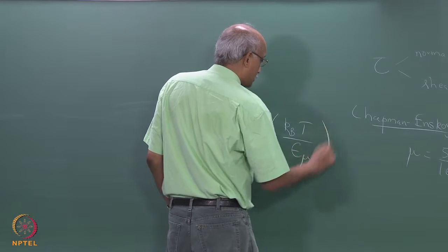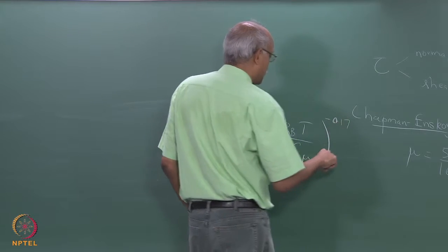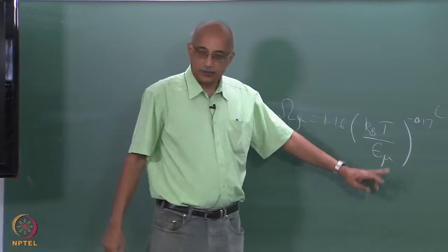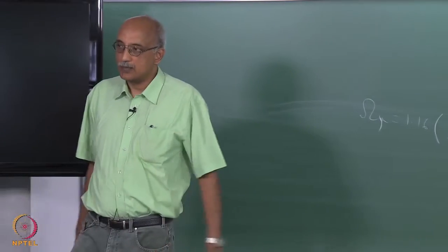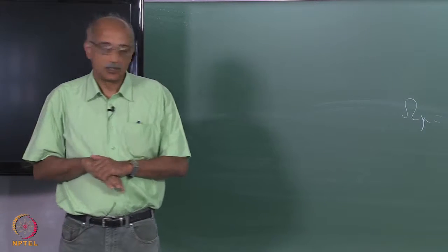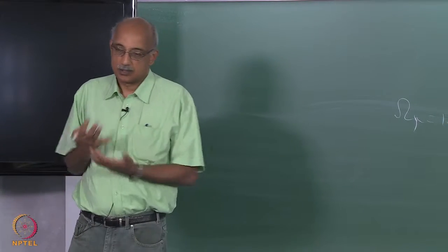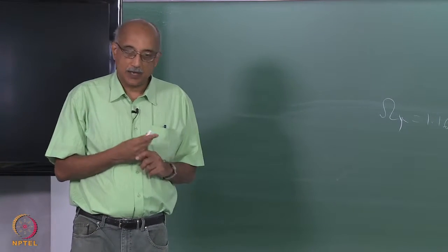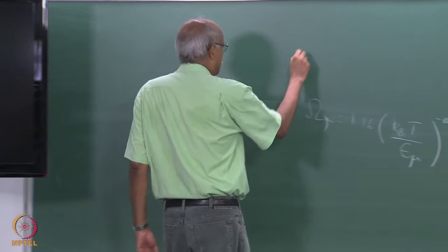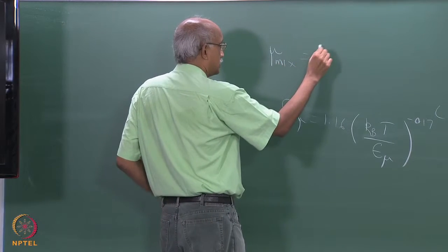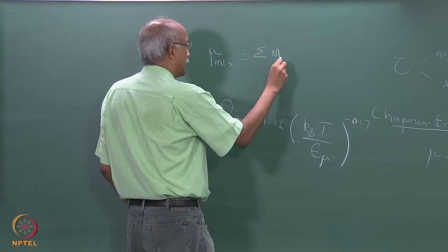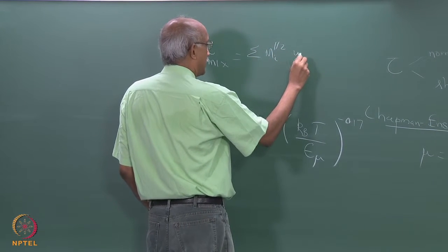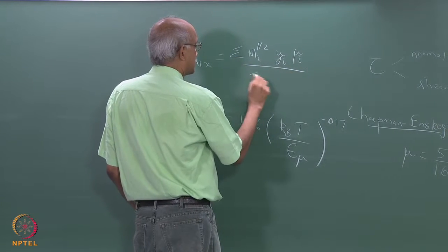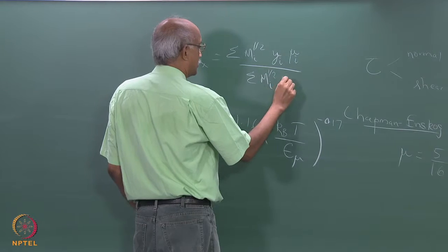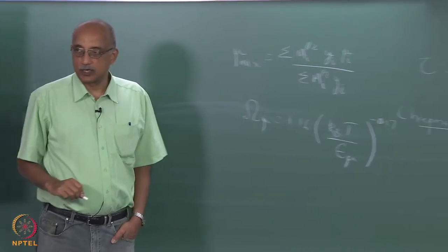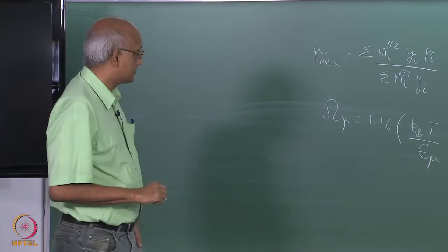So, the omega mu can be written as some 1.16 times KBT by epsilon mu to the power minus 0.17, I think, where this epsilon mu is basically an activation energy barrier for fluidity of the fluid. So, this is a general expression governing the dynamic viscosity of a fluid. If you have a mixture of fluids, you can estimate the mixture viscosity as summation of mi to the power half yi mu i divided by summation mi to the power half yi, where again m's are the molecular weights and y's are the mole fractions.